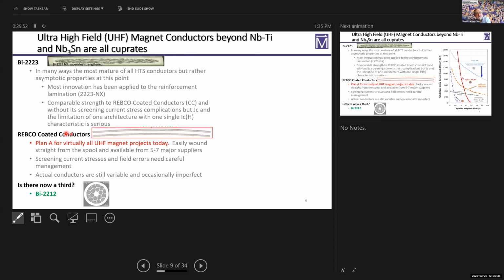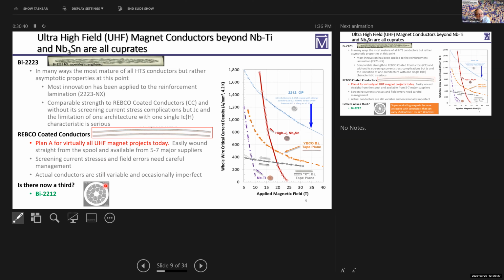It is the least anisotropic of the common cuprate superconductors because the charge reservoir layer has fairly good conductivity in it. It's much better, for example, than either bismuth 2223 or bismuth 2212. But we claim, and about 10 years ago we persuaded DOE High Energy Physics, that for reasons that were not at all well understood at the time, you could make round wire forms of this bismuth 2212, and it had high critical current densities. So whatever was needed here to get a high critical current density was not needed here. And so we said this needs to be understood because of its properties. And in fact, by virtue of very nice support from high energy physics over more than a decade, this has now got the highest critical current density of any of the cuprate superconductors.